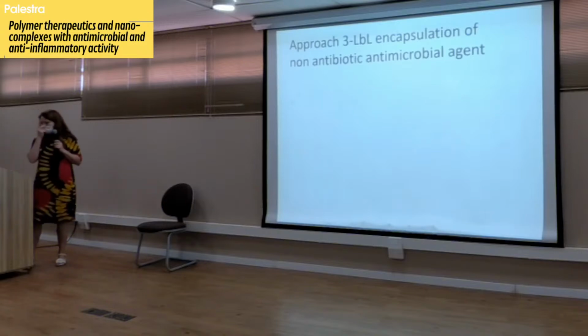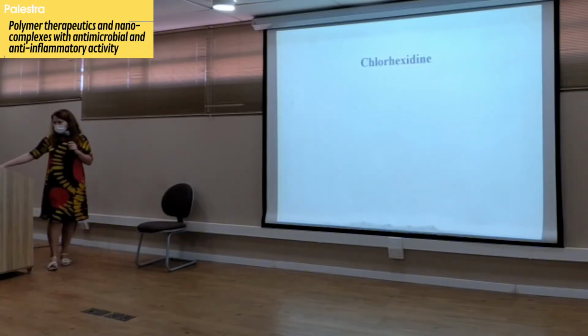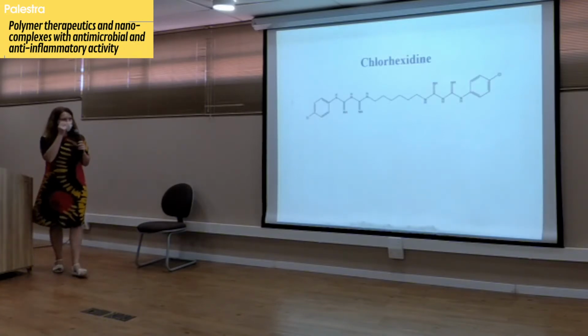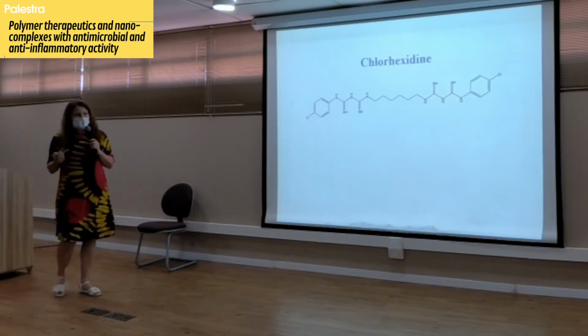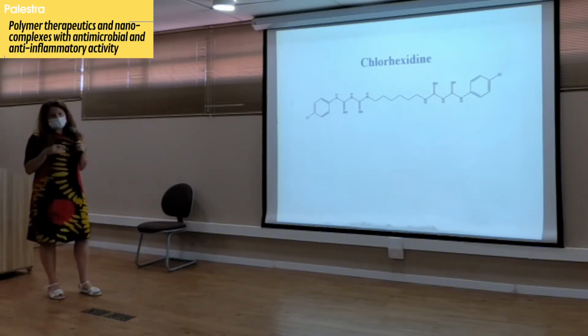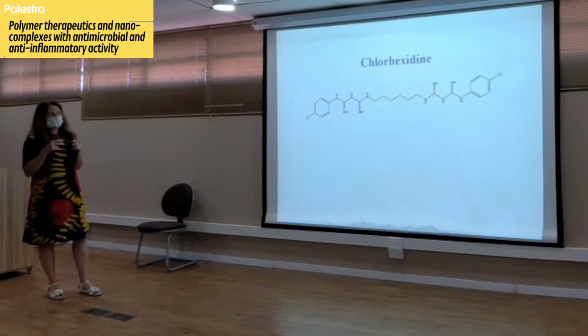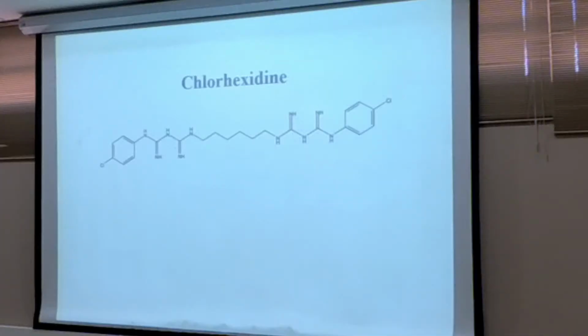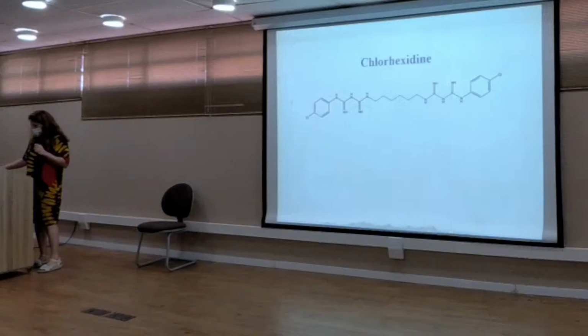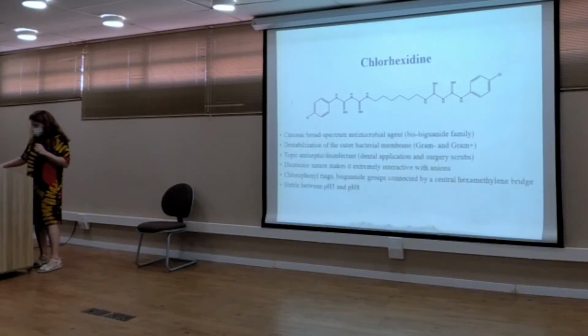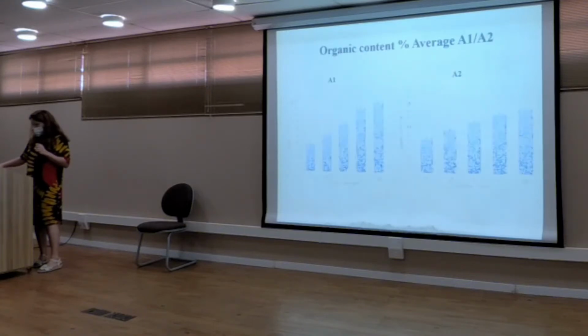Thank you. Okay, so here I just want to demonstrate some of the technique also developed using layer-by-layer deposition. We use silica nanoparticles as our model construct, but instead of using antibiotics, we use a non-antibiotic antimicrobial, for example chlorhexidine, and we encapsulated that within our layers.